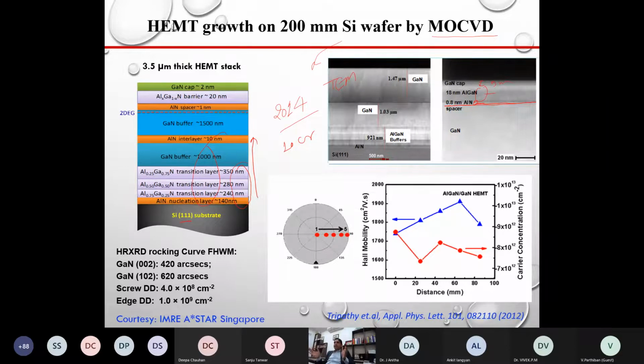So these samples are grown on an 8-inch wafer, and on the 8-inch wafer we can get many samples. First, on the wafer, we have done Hall measurements. We measured how much the 2D electron gas concentration is and how much the mobility is. The mobility is around 1800 centimeter square per volt per second. The carrier concentration we can measure at different points, because whether the carrier concentration is uniform or not, that also we can optimize.